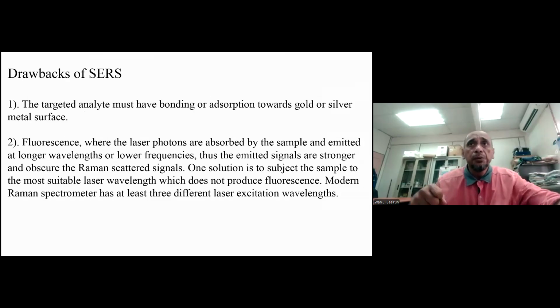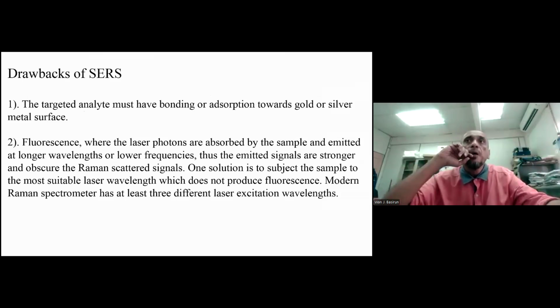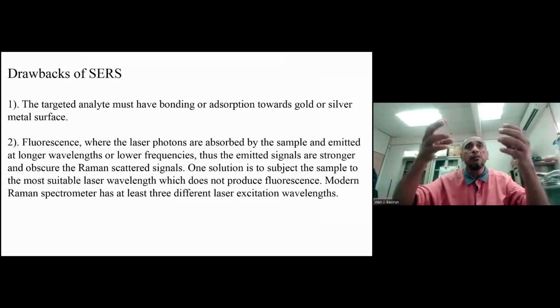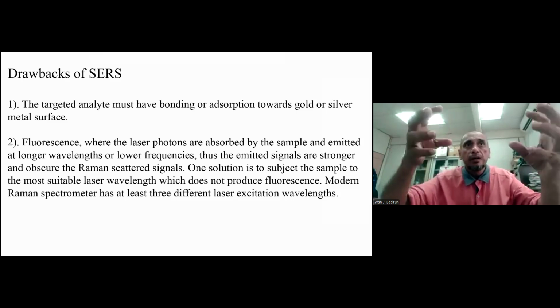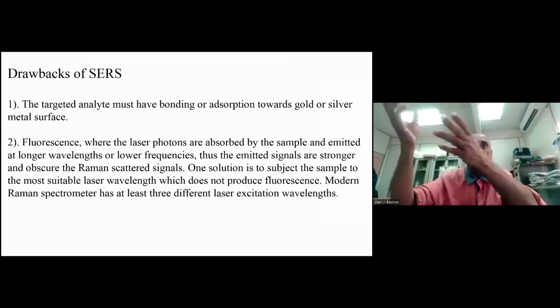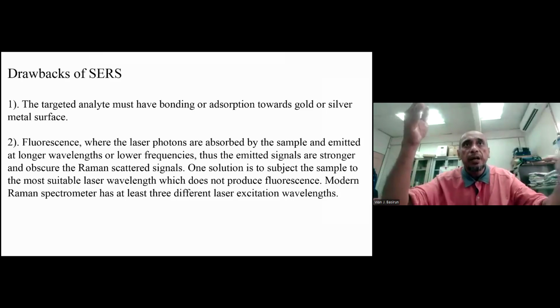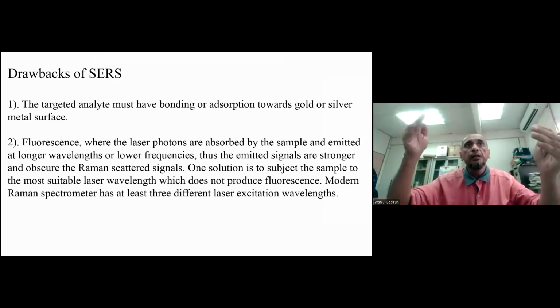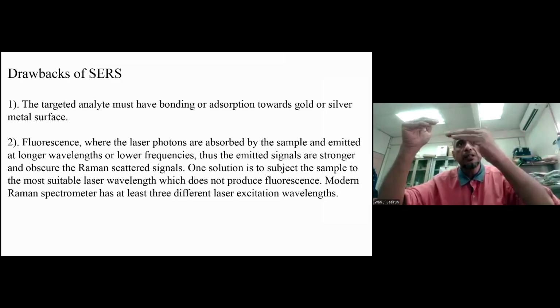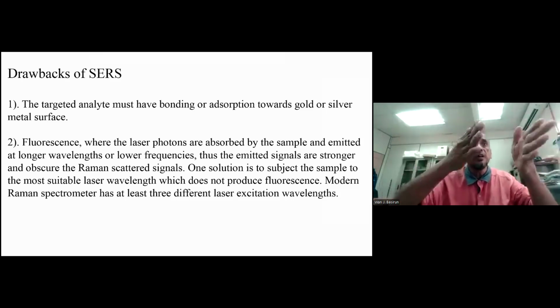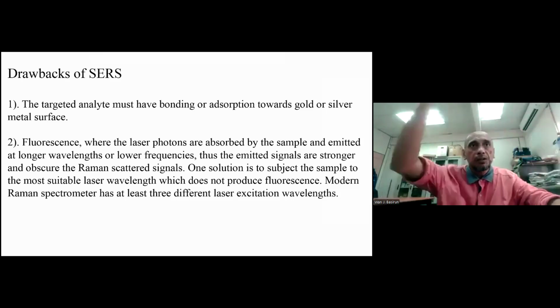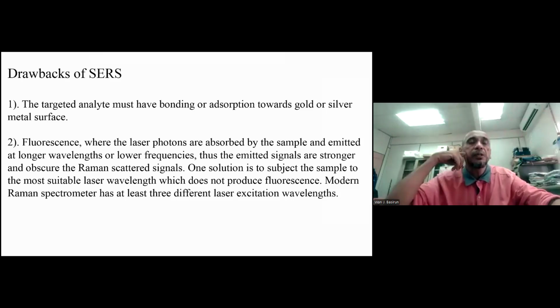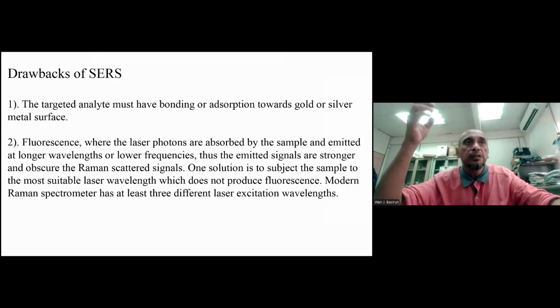Okay, so one solution is to select the most suitable laser wavelength which does not produce fluorescence. For example, before starting a Raman experiment, we used to run the fluorescence first. When you have a pyridine molecule, run the fluorescence spectroscopy, get the result, and make sure that the excitation laser wavelength is not on the same wavelength as the fluorescent peak in the fluorescence spectrum. That is one strategy.